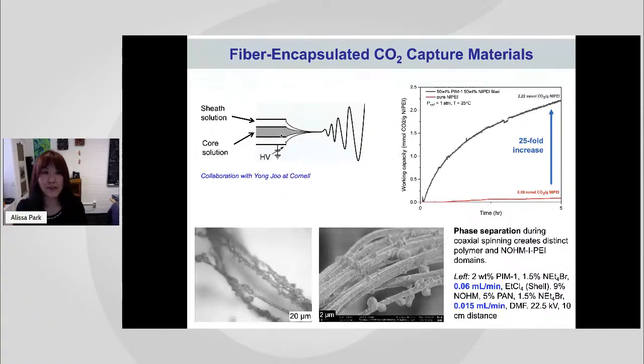So this is our electrospun fiber made by our colleague at Cornell. It's not perfect yet. If you look at the middle picture, there's a fiber which is a pretty good size, about 2 micron plus or minus a little bit, but it still has little pockets of non-smooth fibers. Maybe that's okay because it increased the surface area, and it kind of showed in our data on the top right. Compared to NOHMs, we had a 25-fold increase in CO2 capture rate. It's becoming really interesting to capture CO2 with minimum pressure drop.